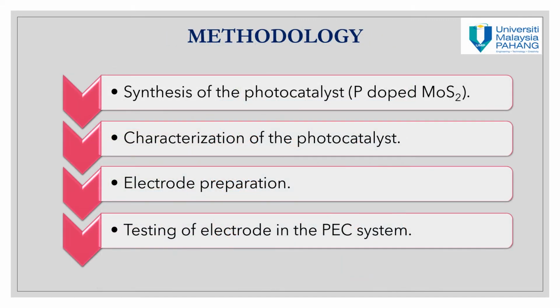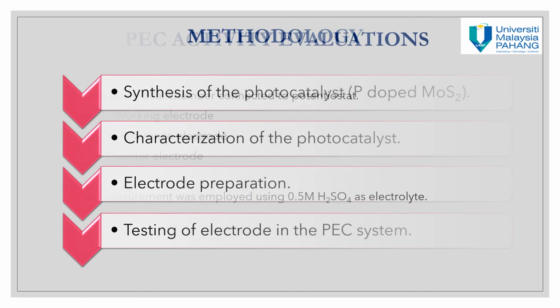In this research, the phosphorus doped MoS2 was synthesized by the hydrothermal method and then was subjected to various characterizations. After that, the electrode was prepared by the ink brushing technique and the electrode was tested in the PEC system for the hydrogen evolution reaction activity.